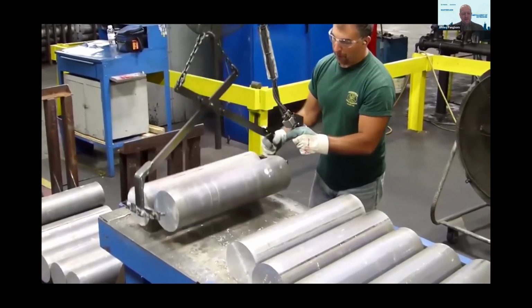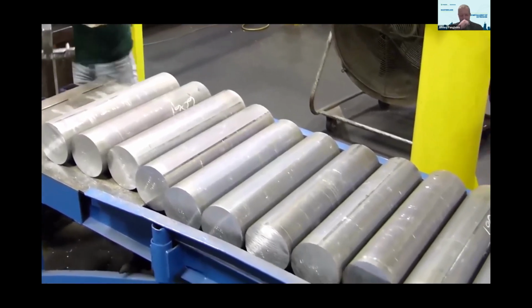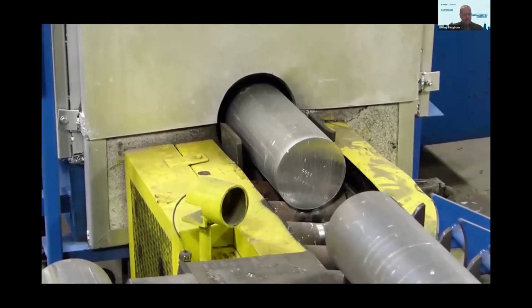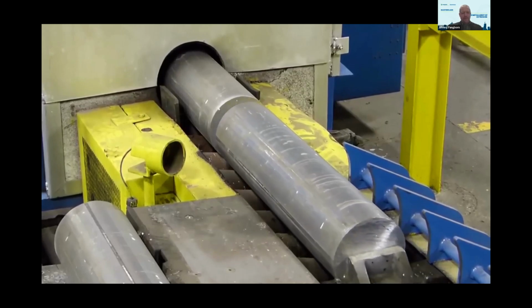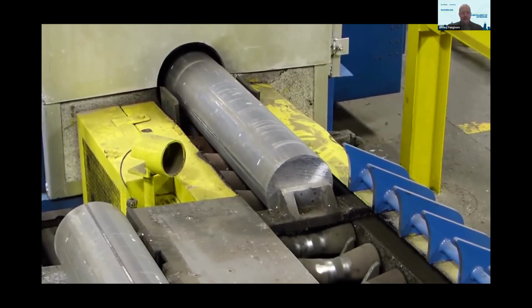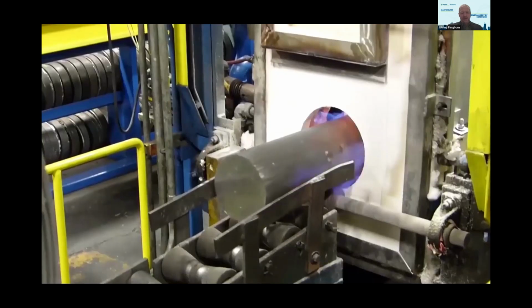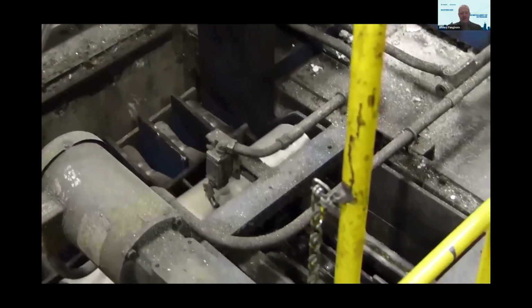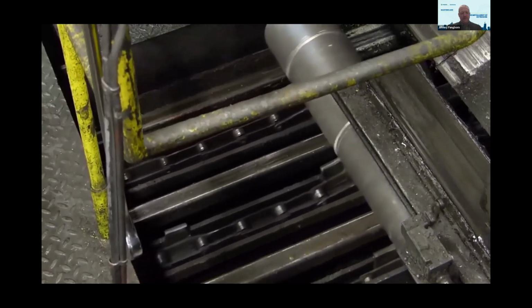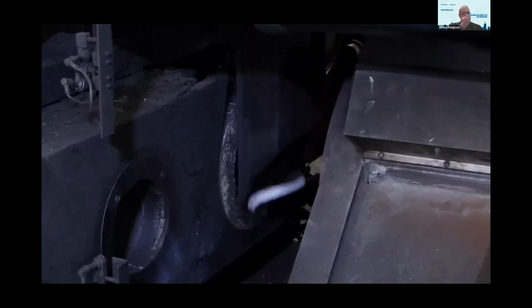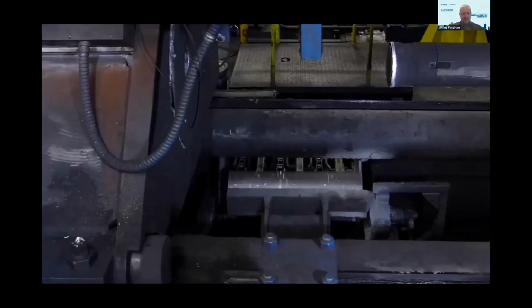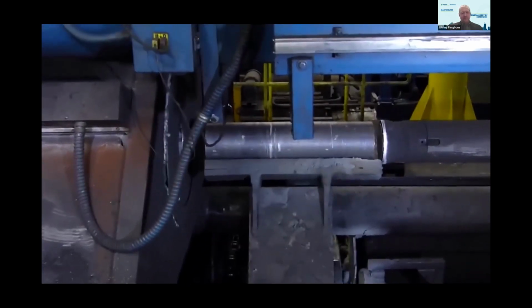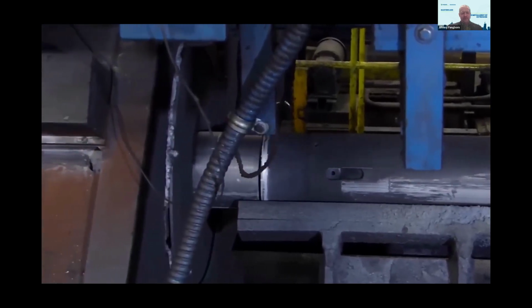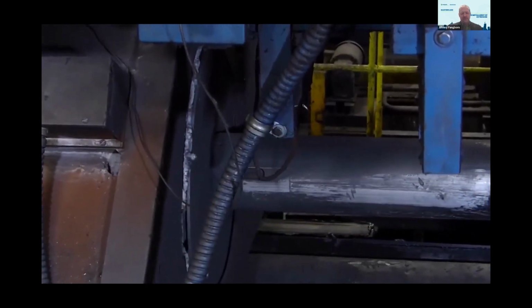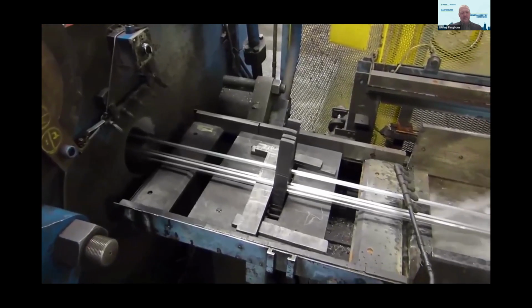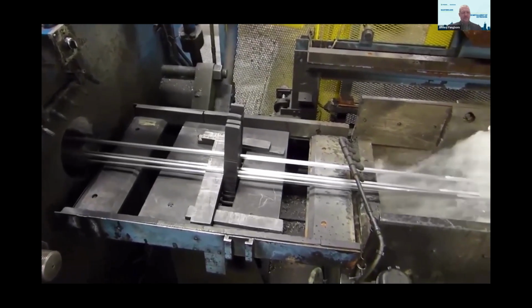Specified aluminum alloy cast in log form and pre-cut to uniform length is known as a billet and is first placed into the billet furnace, where it's heated to almost 900 degrees Fahrenheit. The billet then exits the furnace and is transferred to the extrusion press. The excess material from the previously loaded billet is sheared, and a ram pushes the new billet through the container and extrusion press using thousands of tons of hydraulic force. The soft aluminum is pushed through the steel die opening to create a fully formed profile.